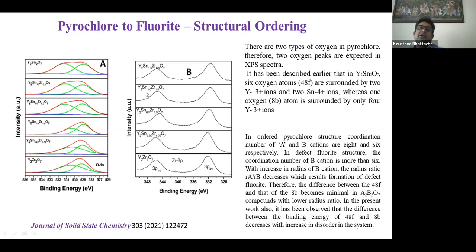Another thing to check: here it's a pyrochlore structure. It is Y2Sn2O7, in which zirconia has been doped on the tin site, whereas Y2Zr2O7 has a fluorite structure. We tried to understand the order-disorderness of the system. It's tough to do from XPS, but we were quite lucky to do that.